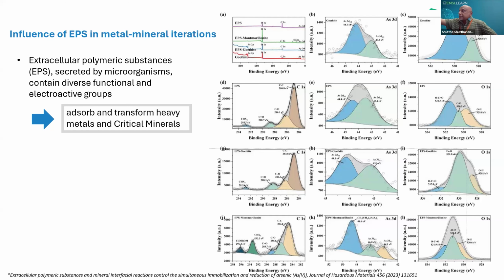So if you look at the bare surface, you see there are 2 peaks in the XPS arsenic 3d spectrum. The blue curve belongs to arsenic in the 5+ oxidation state, and the green one is arsenic in the 3+ state. So as they deposit arsenic on the bare surface, the surface is already reducing some of the 5+ arsenic.